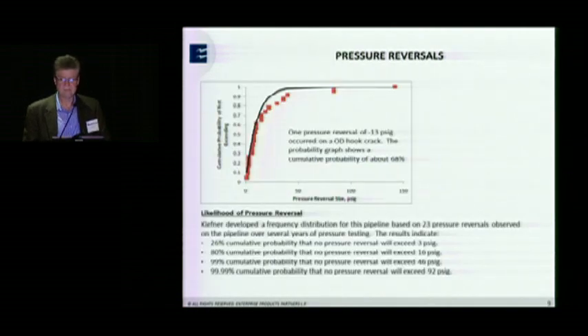Before I get to that, Kiefner Associates looked at this line extensively and looked at some of the pressure reversals that occurred during some of the testing. This is based on a larger population, not this section, but you can see that in this case we had a pressure reversal of about 13 PSI, and if you look at this graph, you've got an 80% cumulative probability that no pressure reversal would exceed 16 PSI. That's just some useful stats, saying that yes, you can get pressure reversals. You may get one as high as 92 PSI, but you have a very low probability of that occurring.